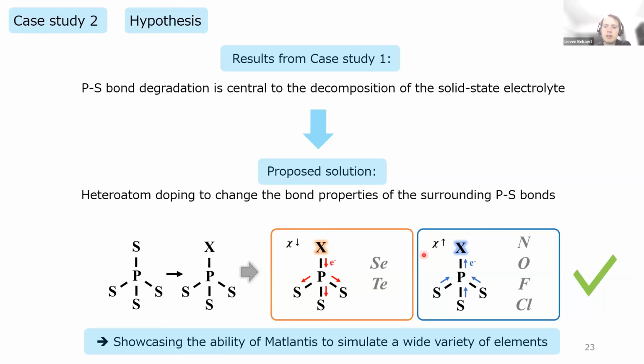And the idea is that because of electron withdrawing and giving inductive effects, you're able to change the properties of these PS bonds. For example, if you use an element which has a higher electronegativity than phosphorus, this will withdraw the electrons from phosphorus by means of inductive effect, and as a result will shorten the PS bonds. And we were able to confirm this with electron localization function calculations. And of course, the opposite effect could happen when you have elements such as selenium and tellurium, which are heavier. So we chose these elements based on the fact that they're in the same group as sulfur, or they're close by and have different properties such as radius and valency and so on.